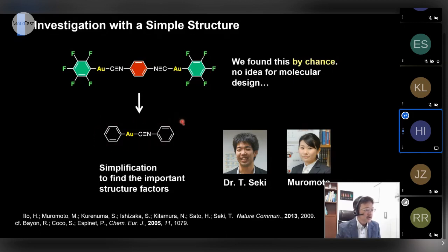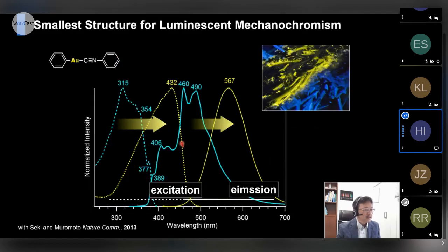Surprisingly, this is a very simple compound, but there was no example of synthesis of these compounds before our study. So we tried to synthesize these compounds, but at first it was not very easy. But one of my students succeeded in synthesizing this compound. So this very simple isocyanide complex shows very nice mechanochromic luminescence properties. This blue part is a pristine, just-synthesized blue color crystal. But after mechanical stress, this compound shows a very nice yellow color change.